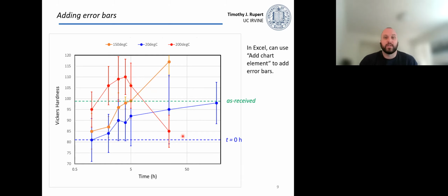So the last thing you could do is show error bars on your data. So here I put Y error bars. These show one standard deviation up, 1 standard deviation down on my data. It looks a bit messier, but it allows us to see where the mean and the standard deviation, the whole distribution, is moving. And that's important because it tells you when to acknowledge differences in that data as being statistically relevant.